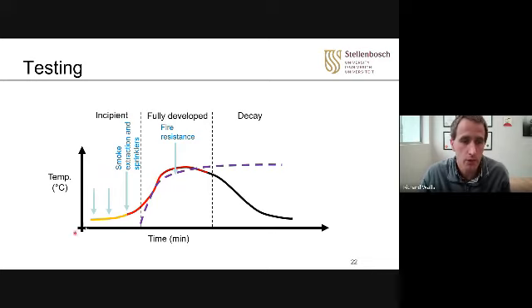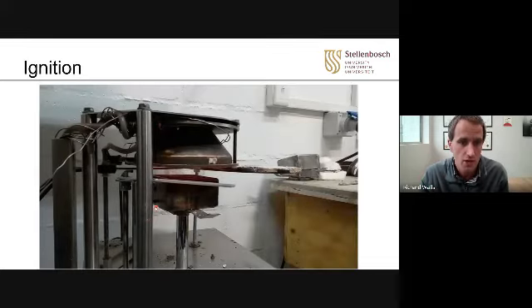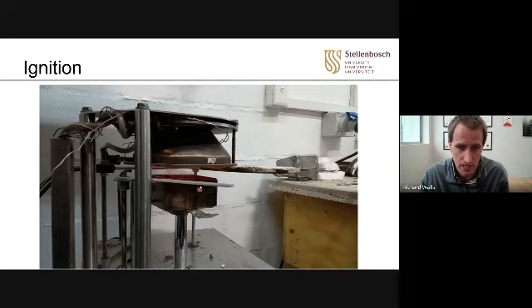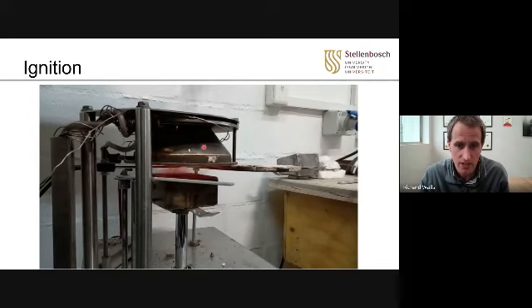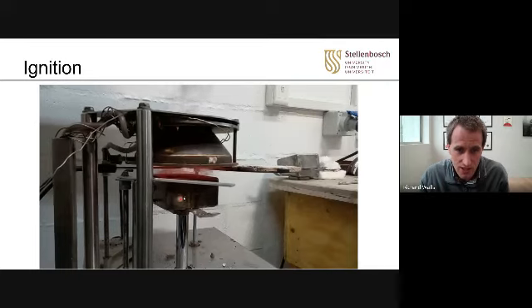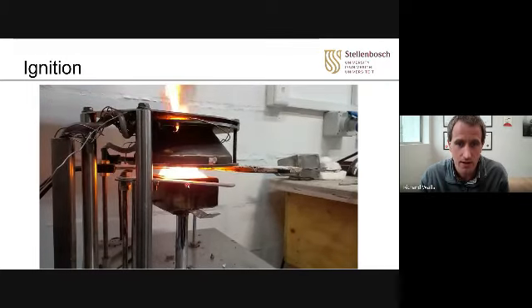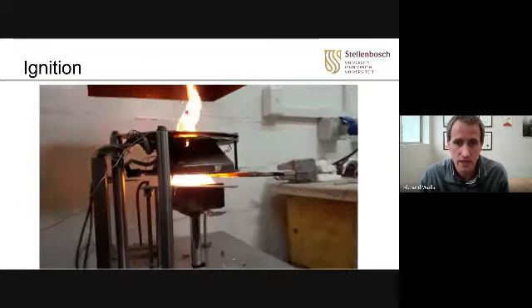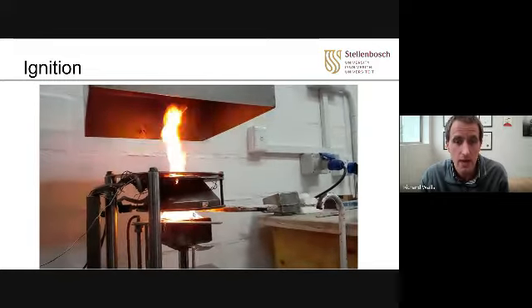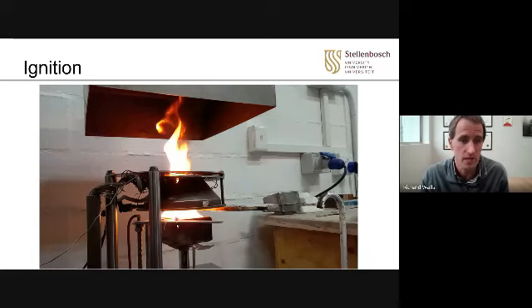So it's got maybe a poor reaction to fire because it does ignite, it does burn, but because it is a thick timber wall, it satisfies fire resistance requirements. It takes a long time to char, it slowly burns through, and so you can get your integrity, insulation, and structural resistance. So this would be a reaction to fire test. A material is there, it's been exposed to high intensity radiation from a cone calorimeter, it heats, it produces pyrolysis gases, and eventually bang, you have ignition. And now you would measure the heat release rate coming off the material, and ultimately this would tell you a lot about the reaction to fire properties of this material. So that is a reaction to fire test.